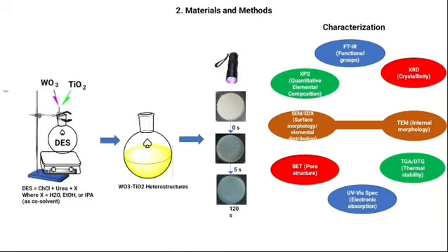The obtained tungsten oxide titanium oxide heterostructures were characterized using different techniques, which include the FTIR, XRD, transmission electron microscope, the TGA, the UV visible spectrophotometer, BET for the pore structure of the material, the scanning electron microscope coupled with an EDX, and XPS for the quantitative elemental composition of the material.